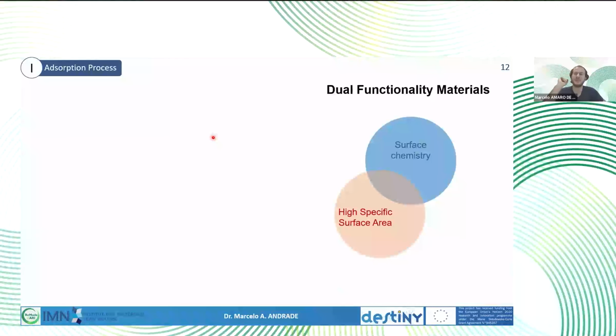So to start with adsorption, during my secondment, well, one step before that, first of all, we needed to define a material to study. And we were targeting materials based, as I said, on surface chemistry and high specific surface area, to enhance the adsorption. But also, we wanted to convert it into batteries or energy storage devices. So it would be better if they were electronically conductive. And when you have electronic conductivity and high surface area, we have electrochemical double layer capacitance, the supercapacitor energy storage type. Also, depending on the surface chemistry, we could see some pseudocapacitance. And our target was somewhere in between that would cover all these parameters, all these characteristics.